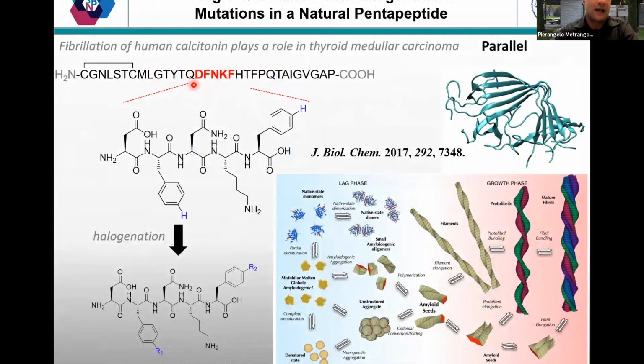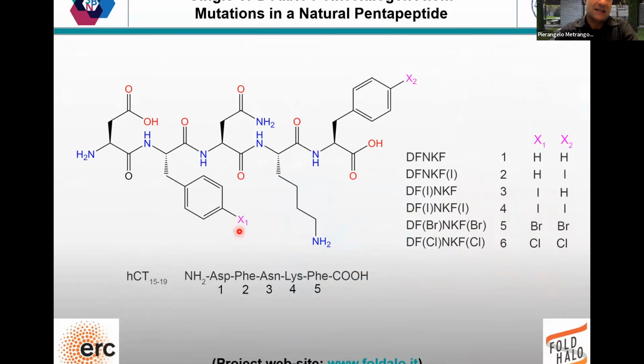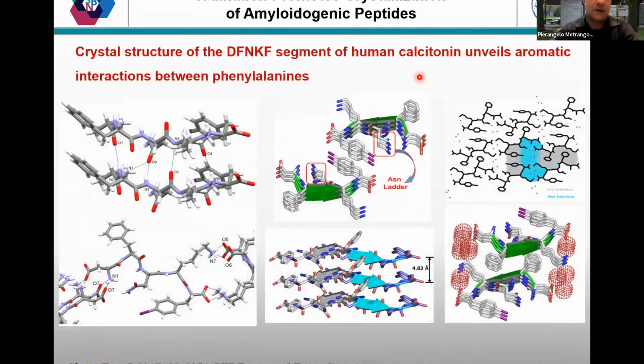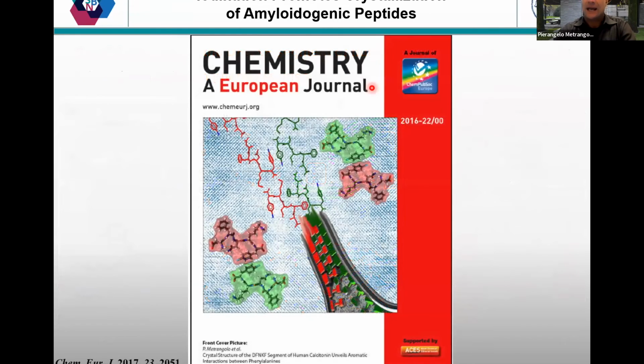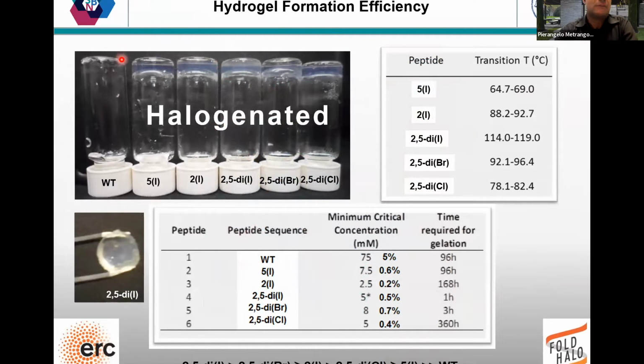Therefore, we took a very well-known peptide able to make amyloid fibrils. So we functionalized the phenylalanine groups with iodine and bromine in two different positions. We were lucky enough to get single crystals of these iodinated peptides because halogenation here is improving the crystallinity, and it's not easy, as you may know, to get the single crystal structure of amyloid peptides. We have nowadays a lot of those structures. And actually, we could study the fibrillation of those peptides which are now halogenated.